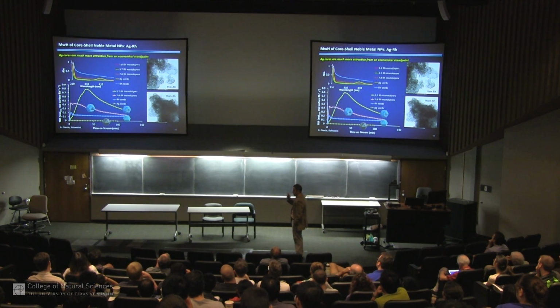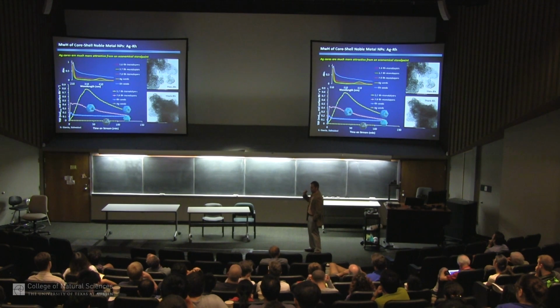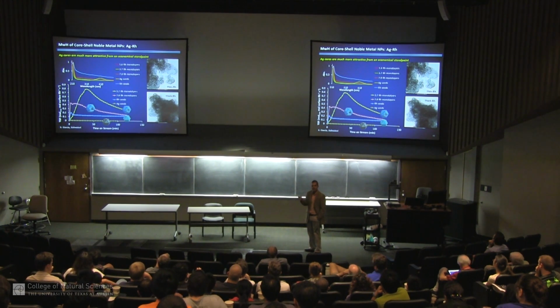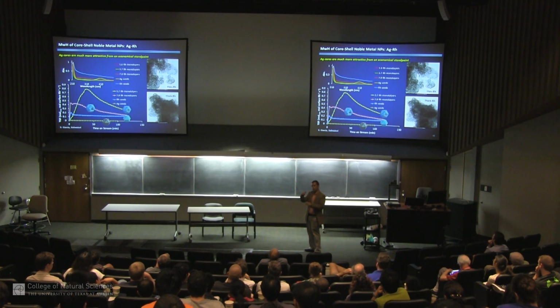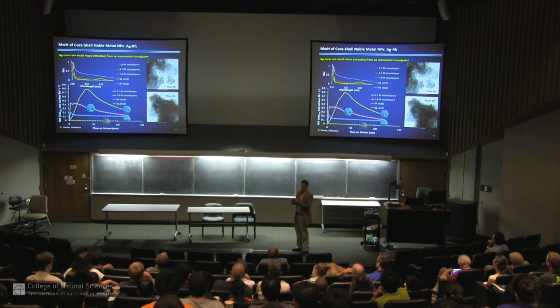Now, one experiment, and this ends the story, and I've got like 4 or 5 slides left and I'm done. One thing we wanted to prove, and it's important in this kind of field, was that when we do catalysis, the core and the shell were not inverting. And there are many examples that are known where you take a core shell particle, you heat it up, you do some chemistry, it'll invert. The core will migrate to the surface and push the surface inside. The easy answer to these problems for rhodium silver and rhodium gold was that they're classically immiscible. No alloys of those are known.